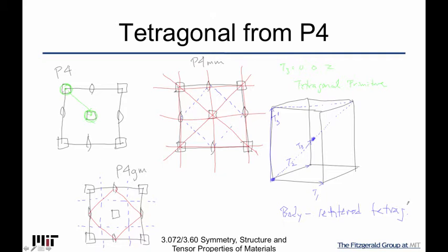The body centered tetragonal form of tin is actually the high temperature version. It just happens that high temperature is, in a way, room temperature. So it's a very interesting material. And when you cool it below 13 degrees, it becomes what's called alpha tin, which is the cubic, actually diamond cubic structure, and it's supposed to have an identically zero band gap.